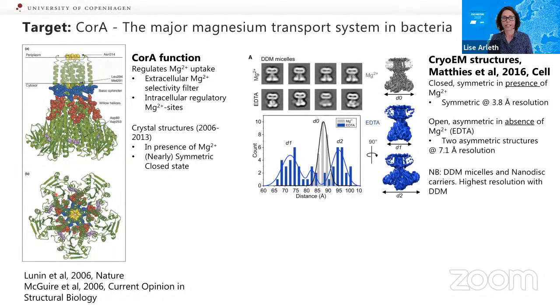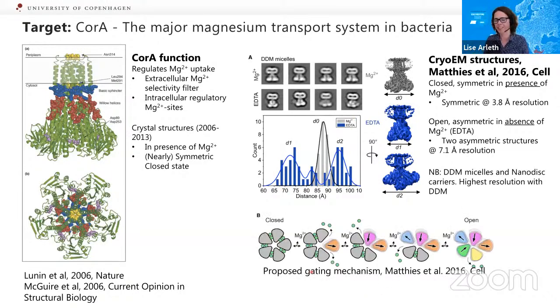And then in 2016 there was a cryo-EM study done by Doreen Matthies and co-workers, where they showed that in the presence of magnesium, they confirmed that they had this almost closed symmetric structure, whereas there was a symmetry breaking when they added EDTA to complex, or to suck out, the magnesium of the structure. So they proposed that this symmetry breaking was the gating mechanism for the magnesium transport, so that it would be closed and symmetric, and then it would gradually open to become active and transporting.